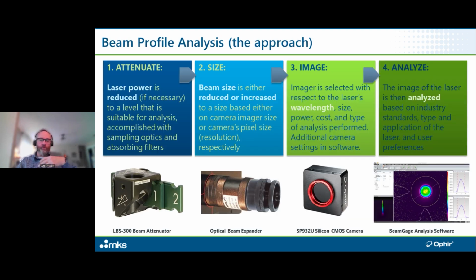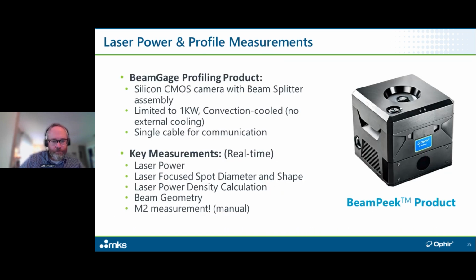I'm just going to talk real briefly about the approach to beam profiling. While using the LBS 300 or a BeamGage device like this, your first step is to attenuate the beam. It needs to be at a power level that's suitable for the camera. Then it needs to be sized correctly. It's very possible that your beam size may be too large or too small for the resolution of the camera, or too large to fit on the camera imager. So there may be some sizing that you need to do. Once the beam is attenuated with respect to power and sized properly, that's when you image the beam, and you take that image and send it to the software for analysis. So that's basically the general approach to beam profiling.